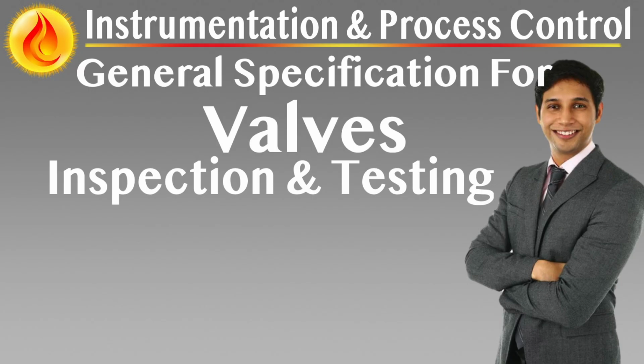Where valves incorporate hard-facing or weld overlays on seating surfaces, additional testing is required to verify the integrity of these layers. This includes hardness testing using portable Rockwell or Vickers instruments, bond strength evaluation where specified, and visual examination for cracks, porosity, or delamination. Weld overlays must meet minimum thickness and hardness requirements defined in technical specifications and welding procedure qualification records, PQRs. Evidence of welder qualifications and process parameters must also be maintained and submitted upon request.